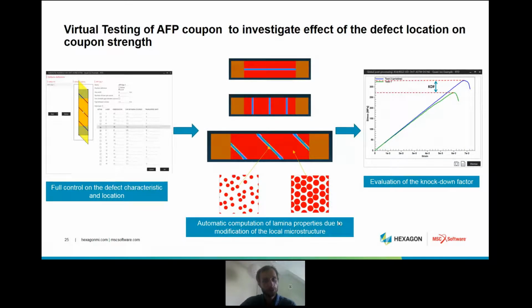So if we start from the lowest scale that we showed on the previous slide, we first want to have a look at the coupon level to understand the effect of defect location on the coupon strengths. And this is made possible with a virtual allowable approach, where the workflow is the following. You first define the defect characteristics and the location, so things like the gap between courses, the transverse shifts, the location versus the hole, and so on. Once this is defined, it's all about correctly simulating the local material properties due to the modification of the local microstructure.